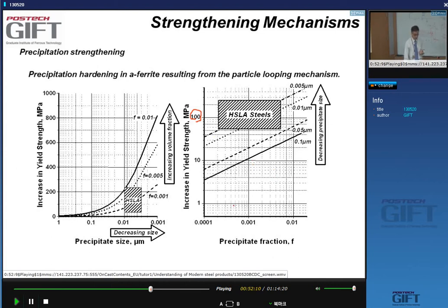Usually you don't get as much, yes? Usually it's of the order of 50 to 100 megapascal, what you get.